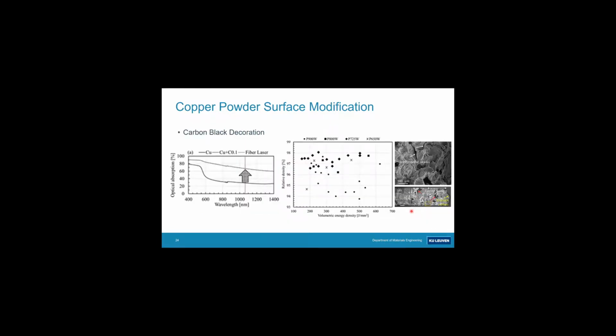Now, you might think, look, whatever you do to your powder which increases the optical absorption will be beneficial, and I intentionally show this slide to make a statement that that is not true. You could simply coat your copper powder with pure carbon, and as you see on the left-hand side, you clearly increase the optical absorption of the powder beds at the near-infrared laser wavelength. But in terms of processing behavior, we needed, again, the same level of very high power levels as we needed for the pure copper at very low scan speed, resulting in very high volumetric energy density.